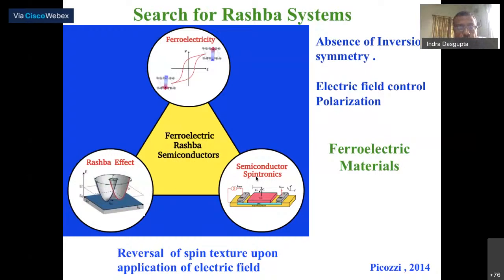Well, so we are going to look for ferroelectric systems where, because of this broken inversion symmetry, you are going to have the possibility of Rashba Dresselhaus spin splitting. And of course, a ferroelectric system where one of the ingredients is a heavy element, because you would also like the relativistic effect to dominate to see this spin orbit effect.